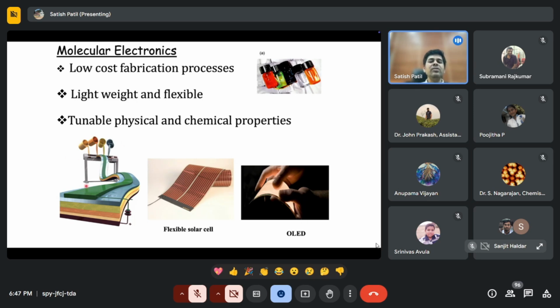You can make thin films of these materials by using this organic semiconductor ink, and you can make very lightweight devices. For example, this is a flexible solar cell. You can make solar cells as very flexible and lightweight devices. If we compare this with silicon, silicon is very heavy and rigid. You cannot make flexible solar cells from silicon using very simple fabrication techniques. Whereas the advantage with molecular semiconductors is you can use this ink and coat on any surface, and make flexible solar cells.